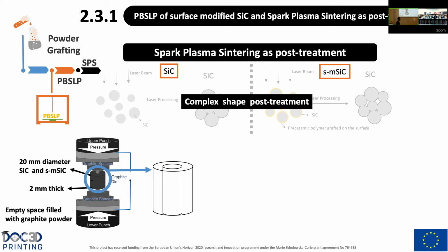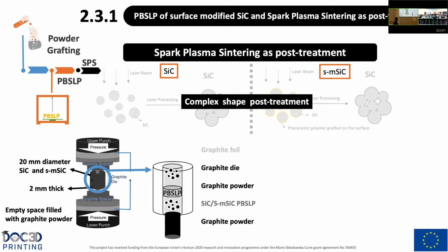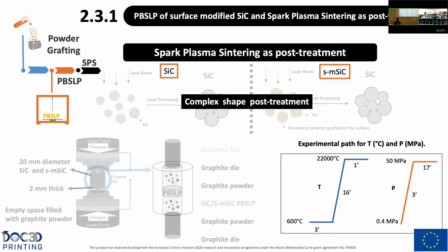To zoom in on the graphite die, here again, we are going to place a graphite foil, then a graphite die. As we have seen, we are going to put some graphite powder. Then we will place the silicon carbide or the surface modified silicon carbide part manufactured by additive manufacturing. Then again, some graphite powder. And finally, the graphite die. And actually, we are going to follow exactly the same experimental path that we used in the previous experiment.